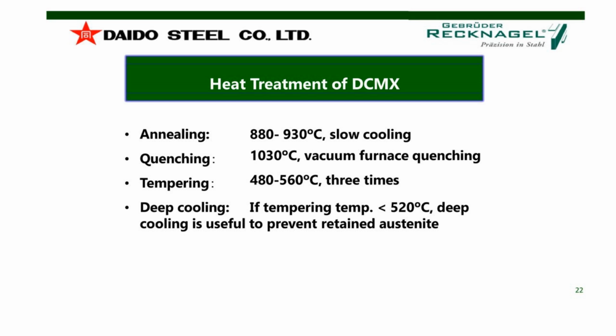And if you use a tempering temperature lower than 520 degrees, it's sometimes very useful to do deep cooling to make sure that the retained austenite switches into martensite. Yeah, the next, please.